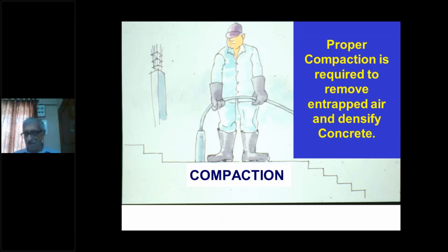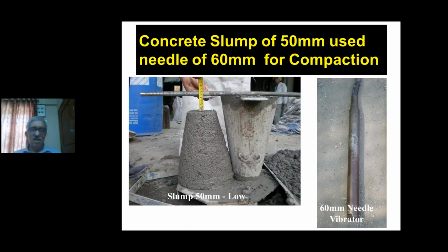Next comes compaction. Concrete using a 50 mm diameter needle, 60 mm diameter needle with a slump of 50 mm is adequate.